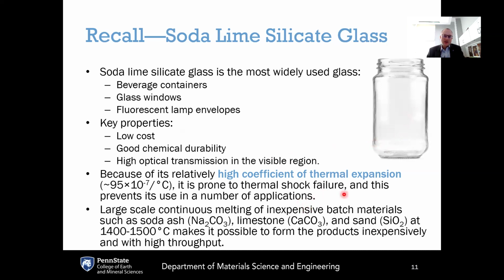One of the downsides of soda-lime silicate is that it has a much higher thermal expansion coefficient compared to fused silica. It's about 95 times 10 to the minus 7 per degree C. And as a result, it's much more prone to failure from thermal shock compared to fused silica. So if you take soda-lime silicate from high temperatures and you quench it rapidly, maybe by submerging it in ice water, it'll probably break. And so you need to be really careful about that.